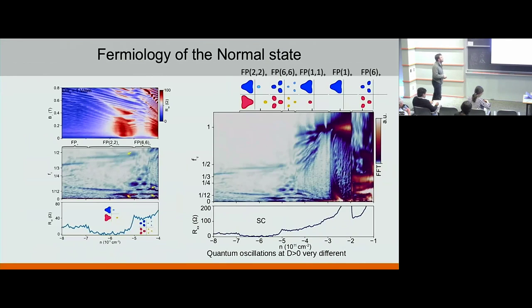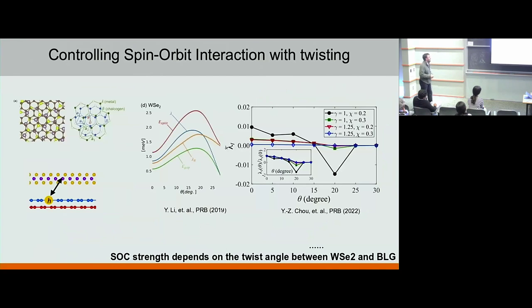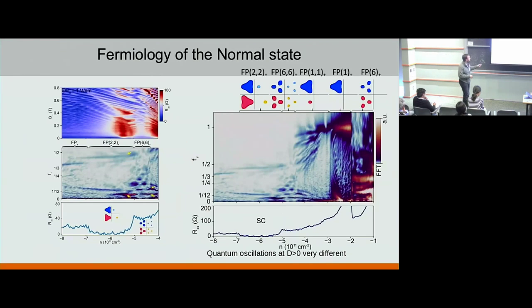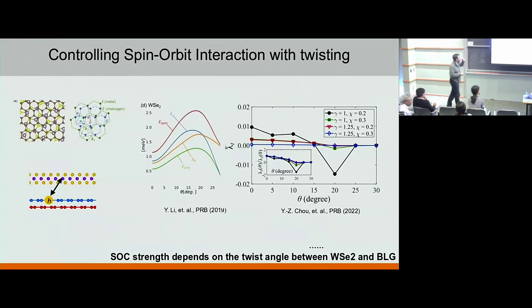Okay, so now you can compare. This was a picture for displacement field less than 0, and this one for displacement field larger than 0. You actually get superconductivity, and you can assign that, in this particular sample, superconductivity lives in this portion of the phase space which has 2 big pockets and 2 small pockets. Okay.